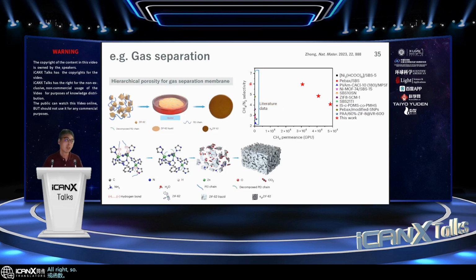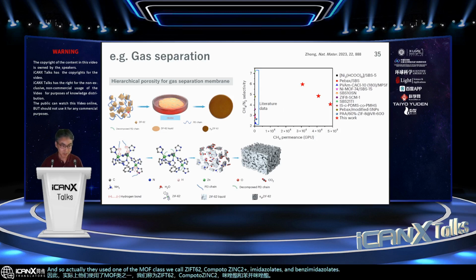All right, so we are still investigating what kind of functionality would be quite powerful by use of the MOF glass. Just one slide, I would also like to introduce one of the very impressive works from Tianjin University. They used one of the MOF glasses we call ZIF-62, composed of zinc 2+, imidazolate and benzimidazolate. They mixed it with polymer to make something like a pancake, okay? And then with further heating, the polymer goes on to give a microporous glass domain as well as mesoporous structure contributed by the removal of the polymer chain. Okay, so you can take a look at this scheme.